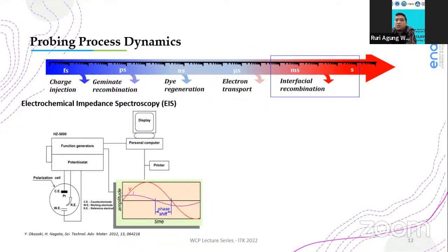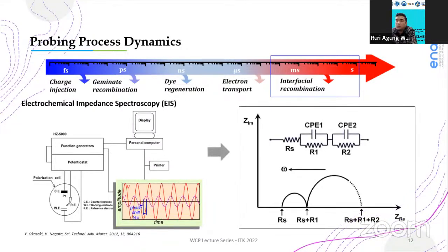And then to probe the slower dynamic processes in the dye-sensitized photocathodes, for example, interfacial recombinations, we use electrochemical impedance spectroscopy. This spectroscopic technique uses AC voltage modulations across the cells and scans over a certain range of frequency. And then the current response was used to calculate the impedance of every interface in the cells, and the impedance response is presented in a Nyquist plot, that is imaginary impedance versus real impedance, and then we can extract electrochemical parameters to evaluate the charge transfer process there.